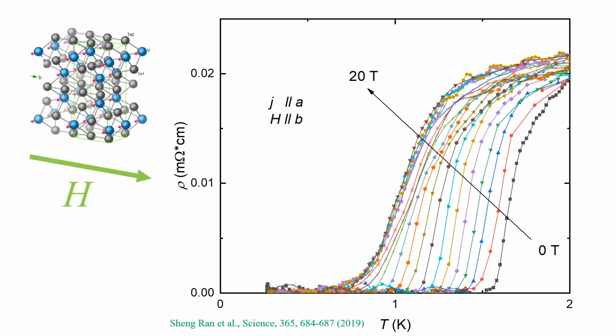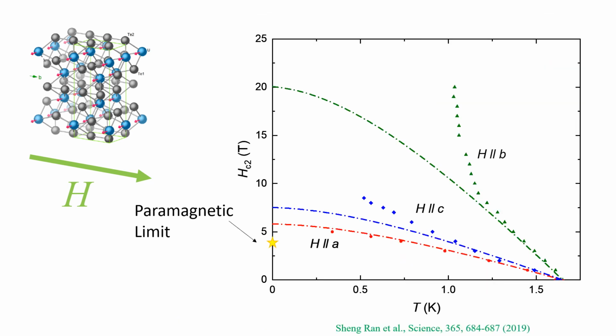This is what happens when I apply the magnetic field along the third axis, the b axis. Clearly, superconductivity remains even up to 20 Tesla. In fact, 20 Tesla is only enough to suppress the superconducting transition from 1.6 K to 1 K. Now, if we put it on the same plot, here it is, clearly it deviates from the theoretical model.